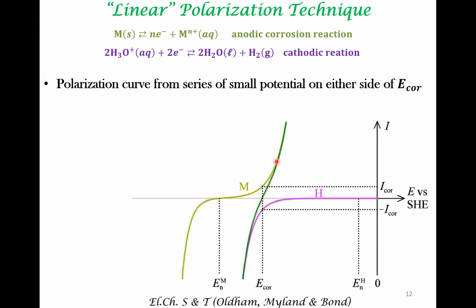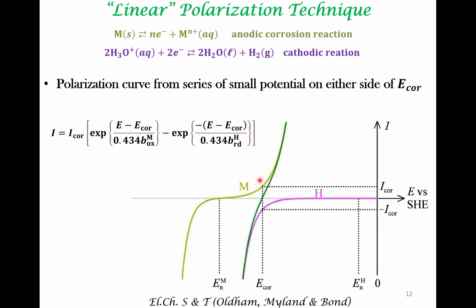Once you get this dark green curve experimentally by varying the potential in this region and measuring the current, you can also fit this green curve to a form as shown here. This is the potential, which is the x-axis. E corrosion corresponds to this particular potential. This form is fitted to the experimental data to get the other terms shown here. What is of significance is this pair of quantities. This quantity is the potential of the corroding sample at steady state, and I corrosion is the corrosion current, which is going to give you a measure of the rate of corrosion.